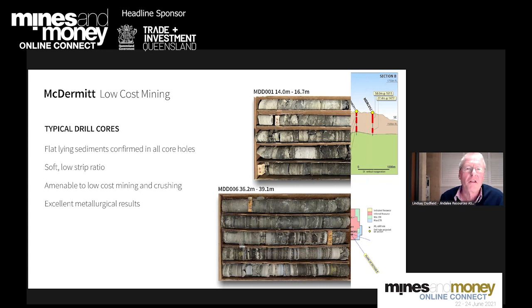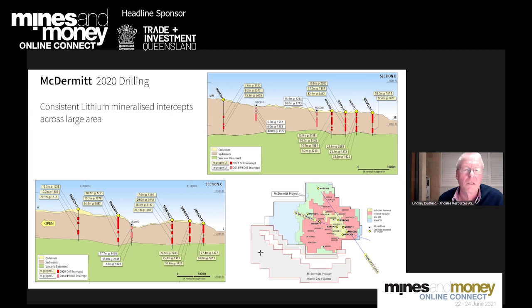Some typical sections. You can see there's a 5-to-1 vertical exaggeration, so we can show this better. But these holes are approximately 400 to 500 metres apart, and basically you can see this broad sort of mineralisation from surface to the volcanic basement below. Our resource, which I'll touch on in a second, is very conservatively calculated. We've only taken the top 100 metres. So we've left a lot of potential sitting below the current resource. This intercept, for example, hole 7, that 35 metres, starts at 99 metres. So 34 metres of that intercept is sitting outside the current resource. So there's plenty of potential to capture more mineralisation by just extending the resource a bit deeper.